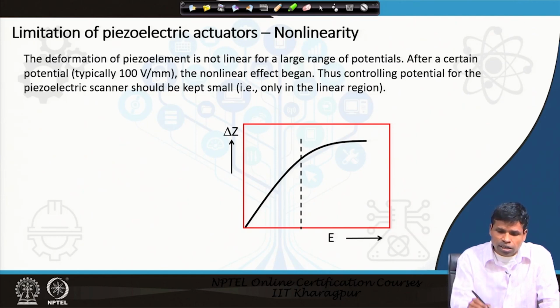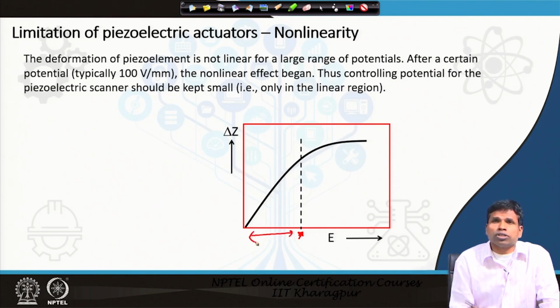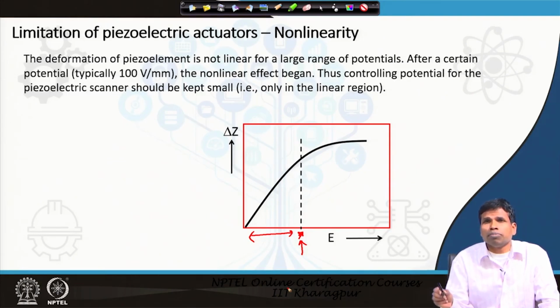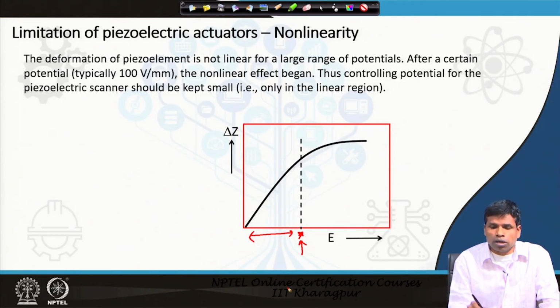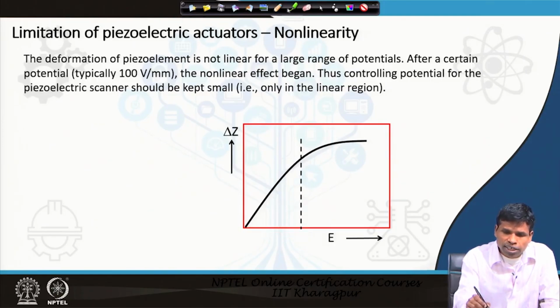As you see here in this plot, del z is increasing up to a potential here, after that it is no more linear. So, in the STM we can only use the range of potential where it shows linear behavior. We cannot use a potential above that. Therefore, there is a limitation on the length up to which a piezoelectric scanner will show displacement. We cannot do the scanning of the sample on a micrometer scale, because the piezoelectric scanner will not allow us to move to any length on the specimen. That is one of the reasons why large area scanning is not possible by STM. This is about non-linearity.